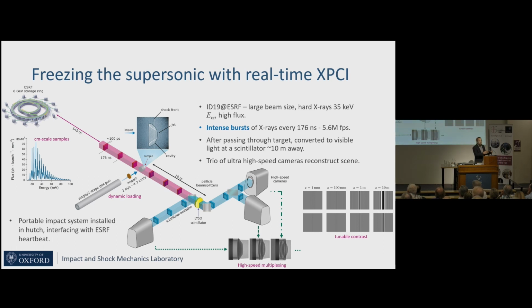We've got, on the one hand, what looks like a big gas gun. Well, that's what we call it, actually. It's a gas gun. And we're launching things at many kilometers per second, and somehow we need to do that careful experiments somewhere where they're also doing very careful precision manipulation and measurements using X-rays. And what we need is we need to study cavities where the dynamics are occurring less than 10 microseconds. That's what we showed before, that the entire experiment is over less than 12 microseconds.